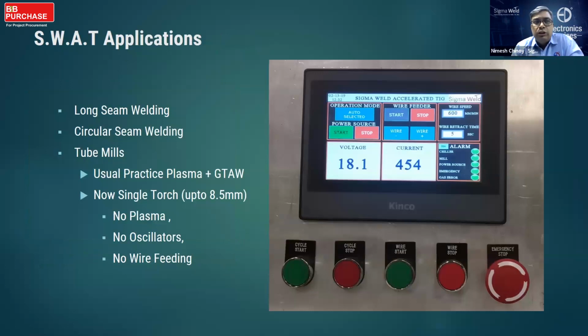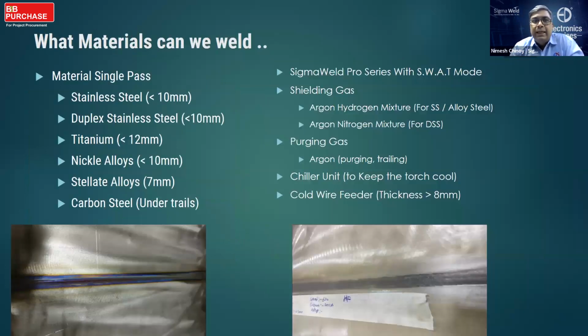This can be used for long seams, circular seams, tube mills. You can weld stainless steel, duplex stainless steel, titanium, nickel alloys, stellite alloys, and to a certain extent carbon steel, all in single pass up to 10 and 12 millimeters.